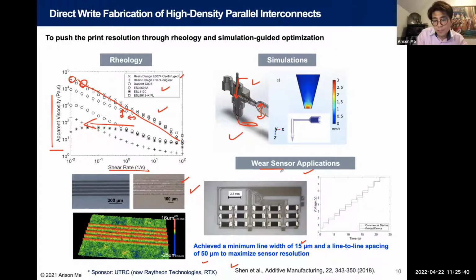So this is a wear sensor. We did not design this. This was done by our partner, Raytheon Technologies. And so you can see a bunch of lines here. It looks as if they all merged together, but they're not. So what happened is, imagine this thing is embedded inside a coating. As the coating wears, it cuts through all these lines. It's going to break some of the circuitry, and as it breaks, it actually sends off a voltage. So by having all these lines as close as possible, you will have a very high resolution wear sensor.